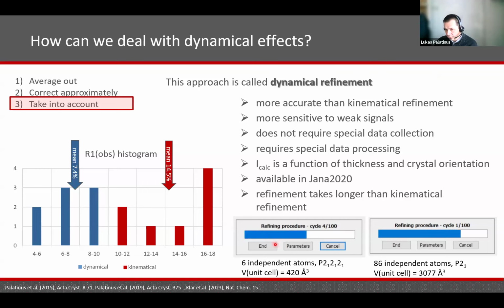And here are 2 examples. One is a very simple structure with 6 independent atoms and a small unit cell. There you see that one refinement cycle takes just a few seconds. If you have a larger structure with 86 independent atoms and a unit cell volume of 3000 cubic angstroms, so that's not a very large structure, but it's already somewhat sizable, then you see that one refinement cycle on a good personal PC takes about 1 minute or a bit more than 1 minute. So that's definitely longer than the kinematical refinement, which takes a second per cycle or maybe a fraction of a second, but it is still feasible.